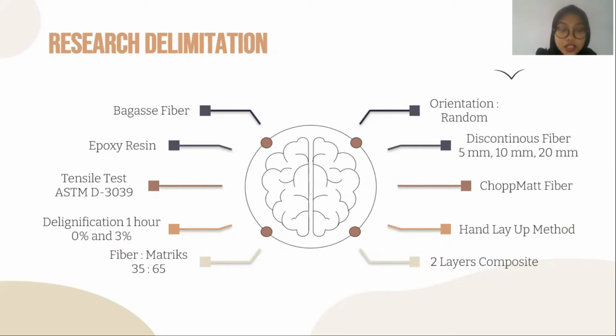In this research, there are several limitations. Namely, the fiber comes from bagasse fiber, and the resin type is epoxy. 3. Testing of mechanical properties is tensile test, and the reference standard is ASTM D3039. 4. The delignification process uses 0% and 3% of natrium hydroxide for 1 hour. 5. The composition of the fiber used is 35%, with the orientation random. 7. The fiber type is discontinuous fiber, with dimensions of 5 millimeters, 10 millimeters, and 20 millimeters. 8. Reinforcement type is chopped matte fiber. And then the method of specimen fabrication is hand lay-up method. And the last, the number of layers in this composite is 2 layers.